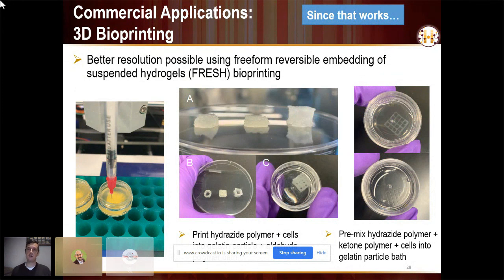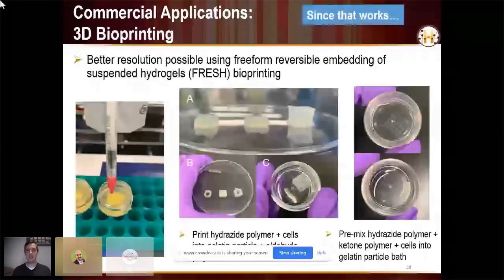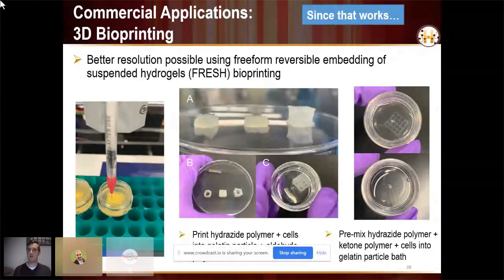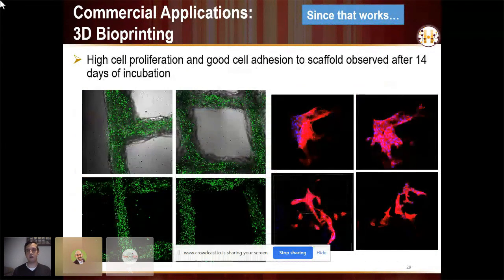The other thing that we can do, which is maybe even more interesting to us right now, is to use ketone functionalized polymers instead of hydrazide polymers, where now the gelation time can be tens of minutes. This bath can actually keep those precursor solutions in place long enough that tens of minutes gelation time isn't a problem. Because if you're doing freeform printing, that's obviously going to be a problem. You'll just create a big puddle or blob at the bottom of your 3D printing well. So in this case, because the materials are pre-mixed, we get much better cross-linking, much better printing resolution, and we've also seen much better cell viability.